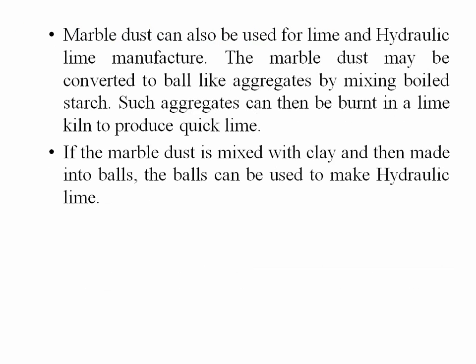Marble dust can also be used for lime and hydraulic lime manufacture. The marble dust may be converted to ball-like aggregates by mixing boiled starch. Such aggregates can then be burnt in a lime kiln to produce the quicklime.